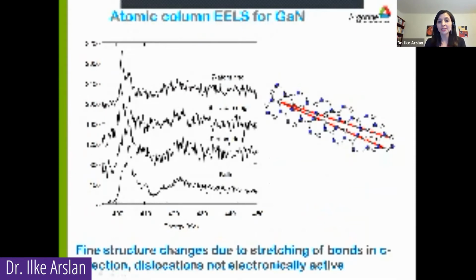And this is kind of a noisy spectrum, but I will point out that we were using an angstrom-sized probe to put directly on top of various parts of the dislocation core. So this is a stacking fault that is connecting two dislocation cores. And we were able to get different spectroscopic signals. So this is the nitrogen K edge, an EELS spectrum. And you can see that in the bulk, this first peak here is just a shoulder onto the second peak.